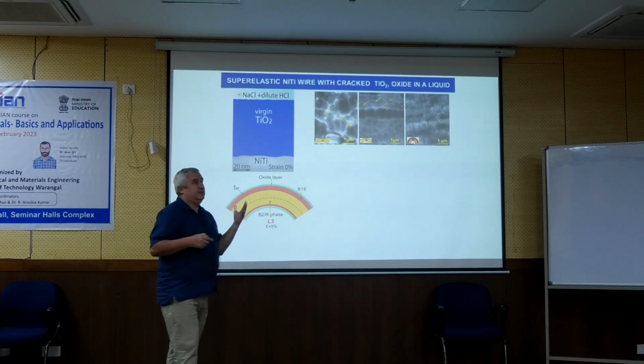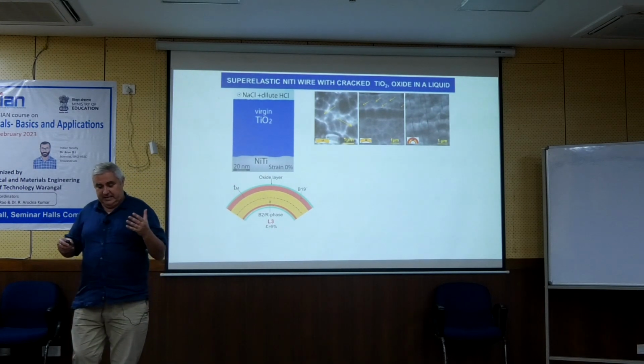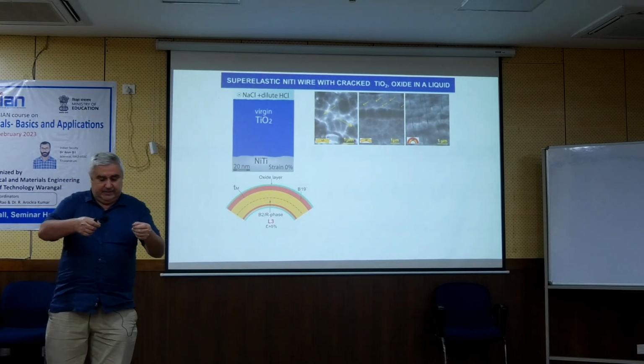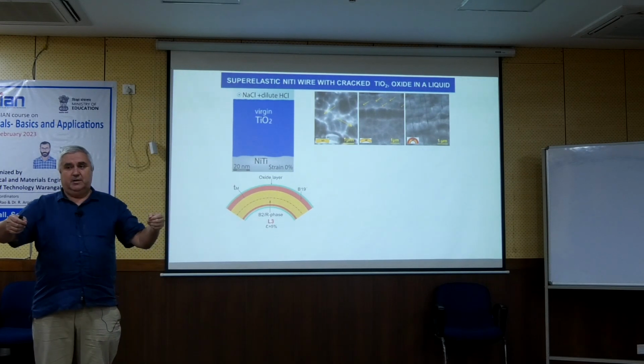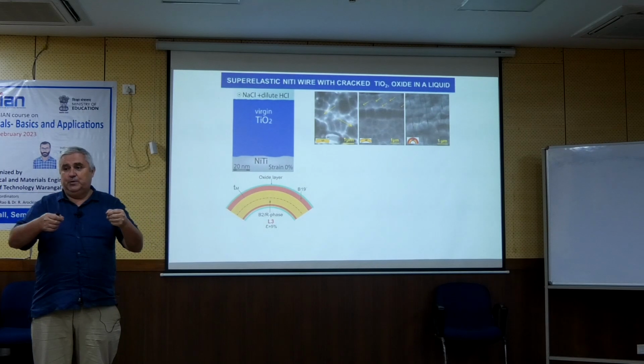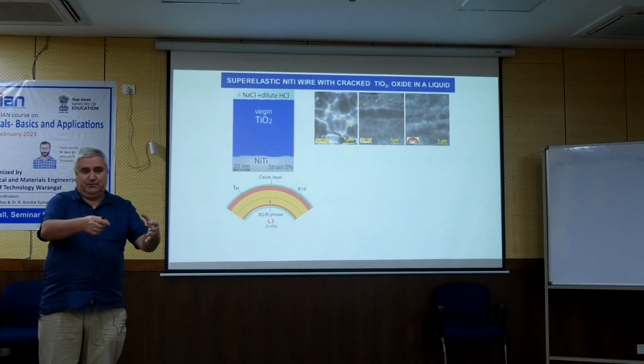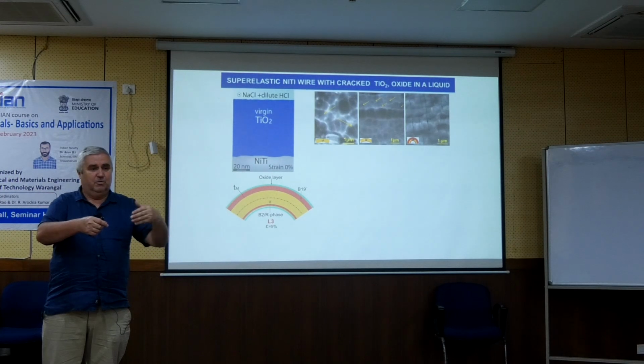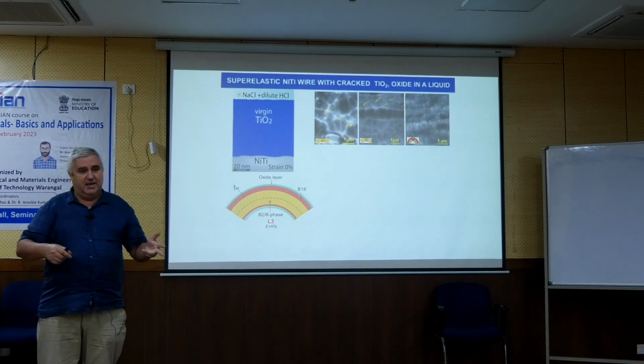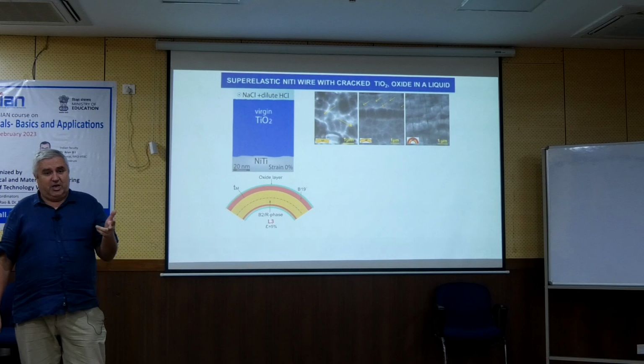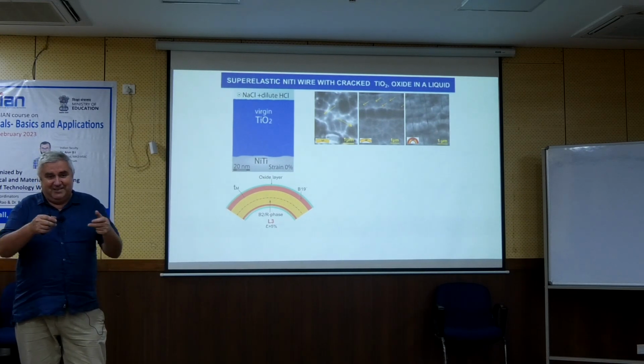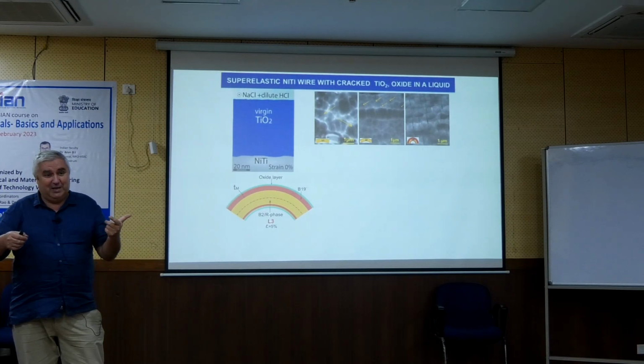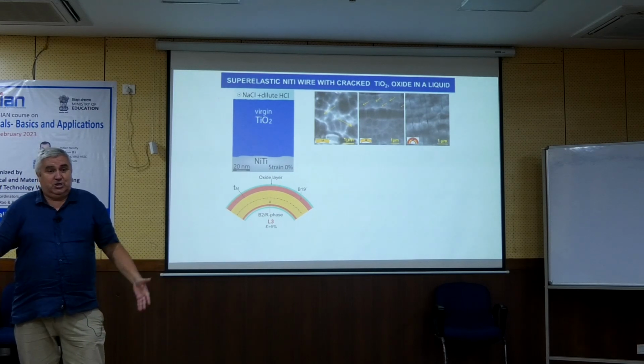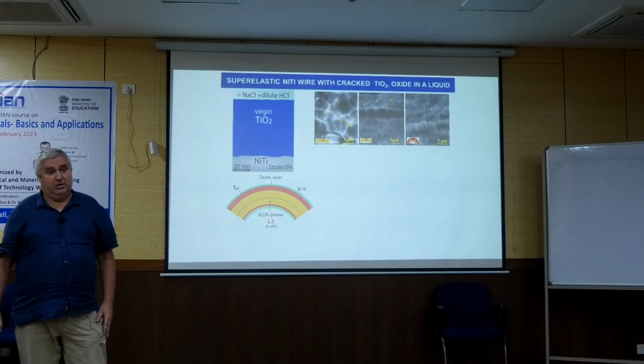So the first experiment, what we did was that we made the sample, stretched it, broke the oxide, and then put it into the biofluid for 1 day, 1 month, 3 months, and after that checked what happens. So when we compared the properties of the wire with the cracked oxide after 1 month, 3 months, no effect. It was the same. So there was no damage. The cracks made no damage.